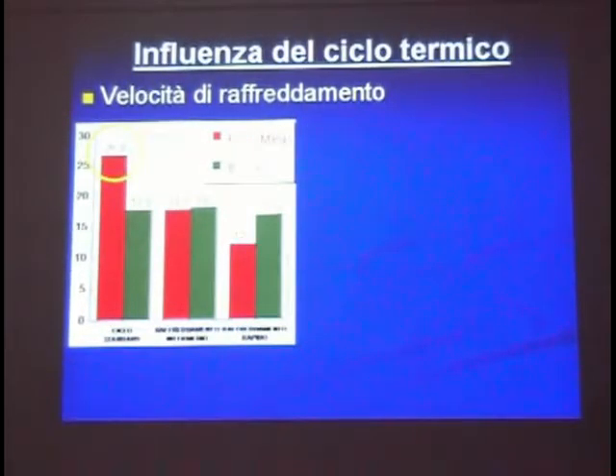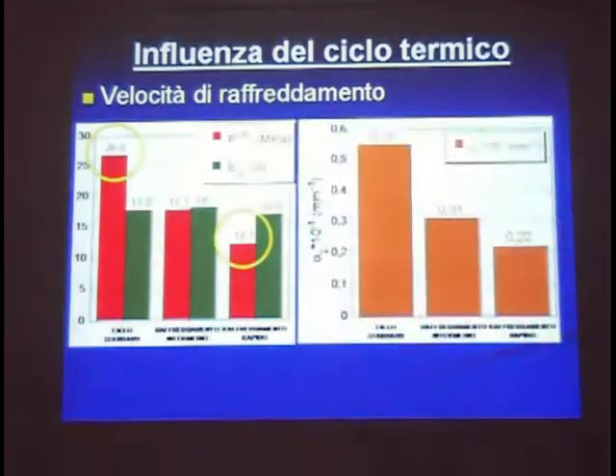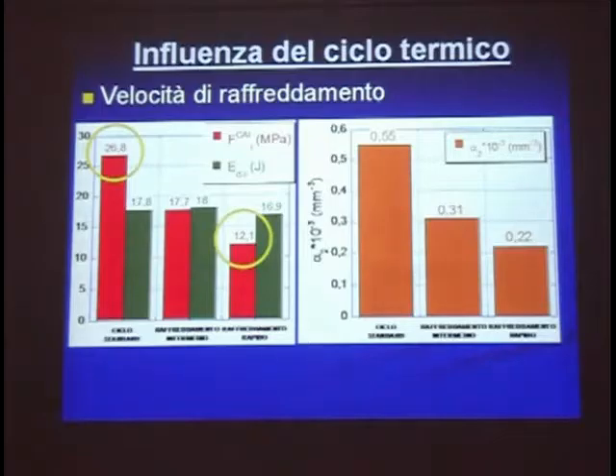This is the cooling rate effect. As you increase the cooling rate from the black curve to the red curve, you get a decrease in the ability of the material to withstand damage, but also a decrease in the slope of the curve in the second part of the plot. And then here you have the summary of the parameters. So the critical strength decreases, while the critical energy stays about the same for increasing the cooling rate. And also the slope of the curve regularly decreases with increasing the cooling rate.